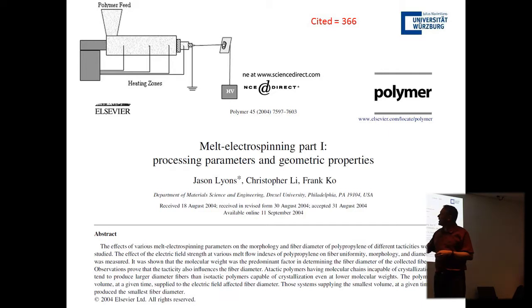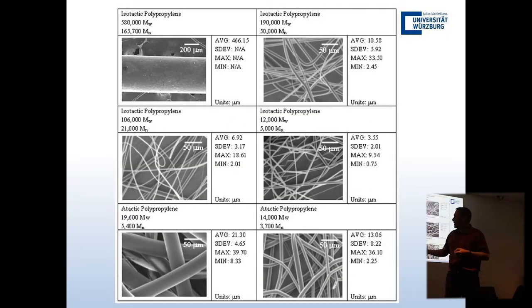And in this instance, they had applied the high voltage to the collector, and they actually fed in the polymer. And actually, with these kind of extrusion-based systems, the flow rate is high, even though we didn't know about it at the time. That low flow rates are really important for getting nice fibers from melt electrospinning. I mean, they were not electrospinning really nice fibers, but they were okay. The average diameter was quite large. So here, almost 500 microns, 11 microns, 7 microns. These are the smallest with 3.5 microns, 21 and 13.